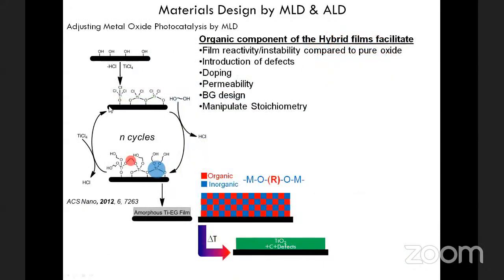Here you can see the step-by-step synthesis of the films, and you can recognize here the inorganic titanium oxide clusters linked with the organic components, which is overall a titanium ethylene glycol film. And by repeating this over and over again, one can deposit this hybrid organic inorganic thin film with controlled thickness. And before it is annealed or during the anneal, one can manipulate and control all these important characteristics that I will show you that result in high performance titanium dioxide thin films with properties that are usually much more complicated or difficult to attain using other types of synthesis methods.